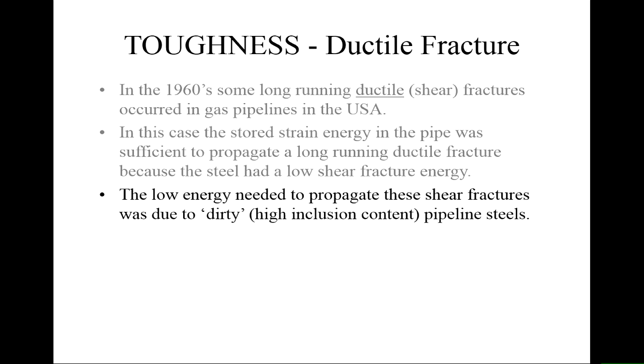So that's why we tend to put a fracture toughness number in the specification as well as a strength, because the inclusions are so small in volume fraction that they make little or no difference to the basic static mechanical strength of the system. But for fracture, they make a huge difference.